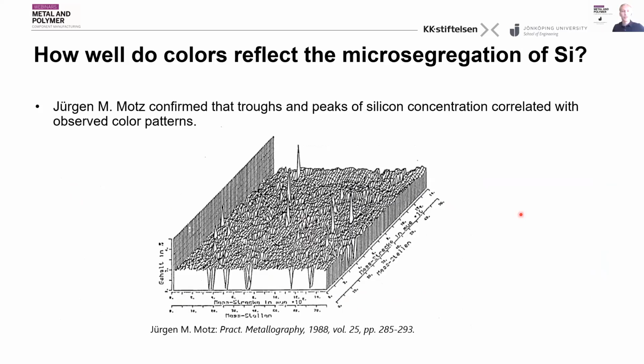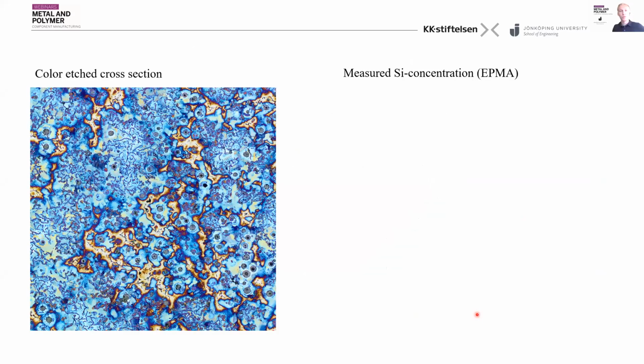So when Jürgen Motz introduced this method, he also verified that the troughs and peaks of silicon concentration correlated with the observed color patterns. However, these height maps that he showed to demonstrate the correlation were not so easy to compare to the color patterns. So in later work, we have tried to compare more carefully and verify that it correlates well with silicon.